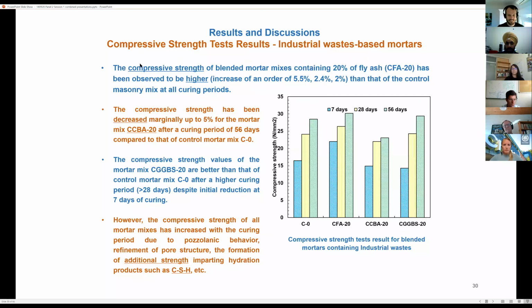Now coming to the results and the discussion. In the case of the industrial byproduct based mortar mixes, we have done the curing up to 56 days, and this work is going on for another 90 days. Here the results are only up to 56 days, and we have seen that at 20% replacement levels, there is no huge difference in compressive strength. This means that the mechanical performance we are proposing is equivalent to that of the conventional mortar mixes, or the conventional PC mixes.